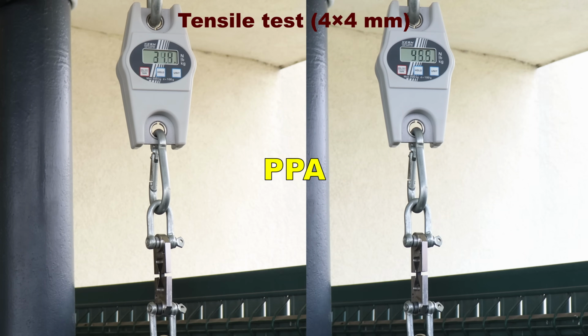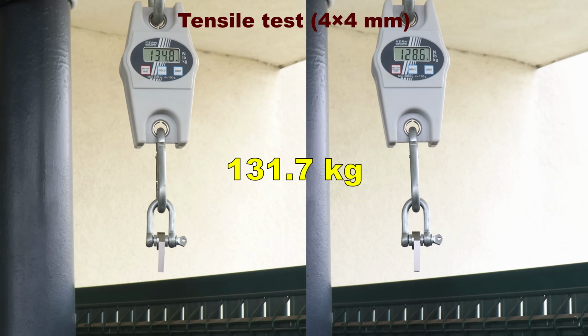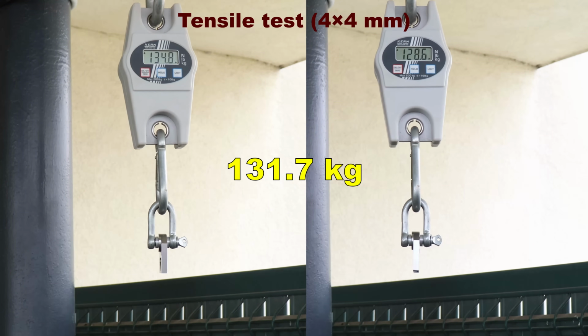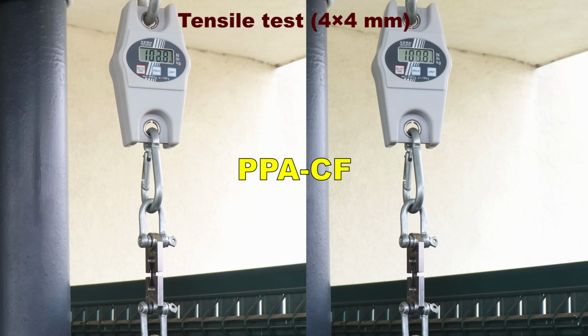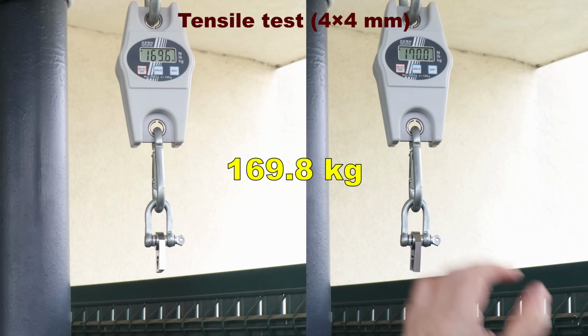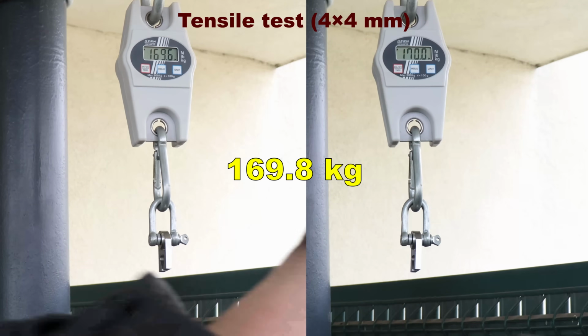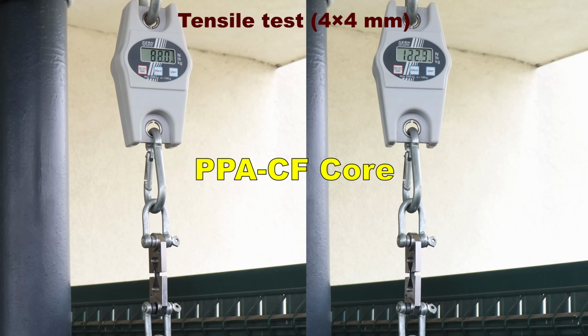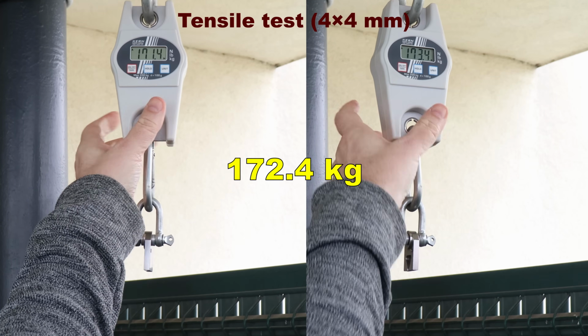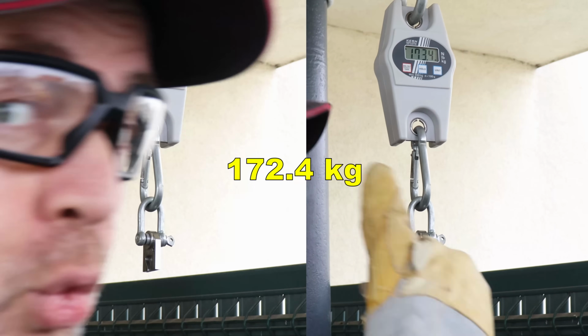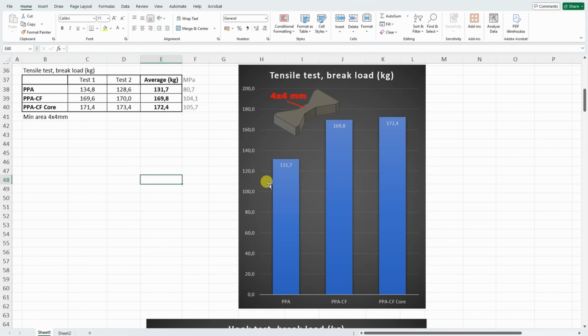The tensile test with horizontally printed test objects, this is PPA, and even this material is quite strong here. And now the carbon fiber version, one of the strongest I ever tested. And now the core, I hope it will be similar, and it is even stronger. So as I mentioned, even PPA is quite good in this test, but two carbon fiber versions extremely strong.